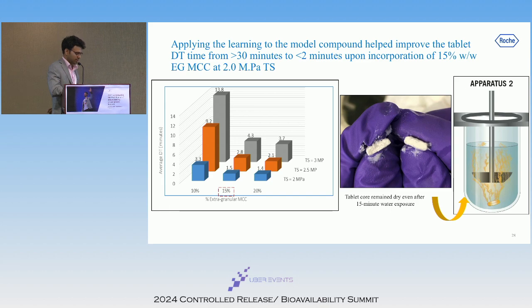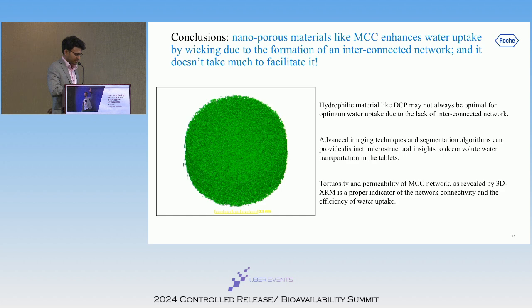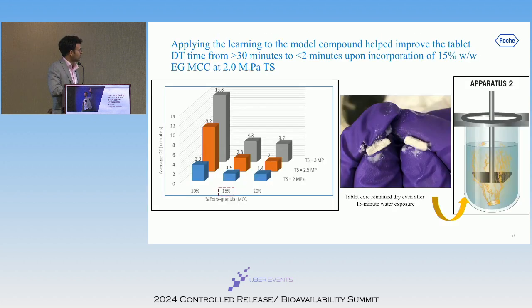And what we see is, with the addition of as little as 15% MCC, we were able to get to a disintegration time of 1.5 minutes, compared to more than 20 minutes that we observed earlier. So this clearly depicts that for tablets that have poor disintegration issues, and where water uptake is one of the underlying issues, we have to systematically and rationally evaluate the problems and find solutions rationally.